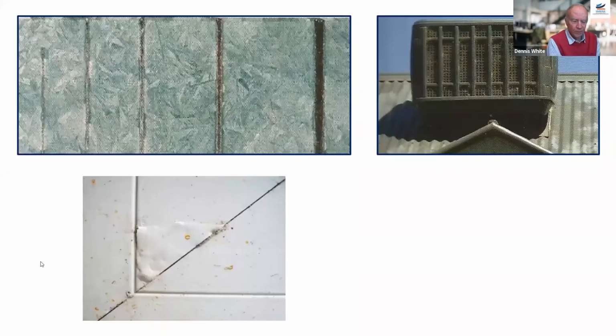And from a cladding point of view, yes, you can get a coating that you can put on the surface. But if you go back to that last slide, the picture in the top right-hand corner shows you the difference that you get between an oven-cured paint, which is on the surface of the pre-colored material when you purchase it, and where you've used air-dried material to touch up the paint. And of course, those touch-up paints are nowhere nearly as durable as your original coating. So if you've got a metallic coating and you've breached it to the point where the gouge is that deep or that big that you're getting rust, you're going to have to constantly go back and attend to that on probably a 24, 36-month cycle. Color-coated material, it's going to look terrible, and unfortunately, you're going to have to replace the clad.